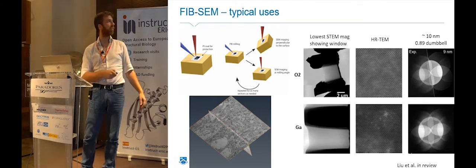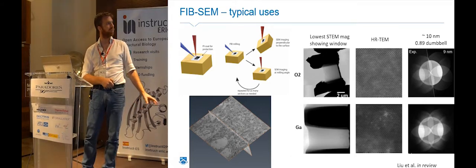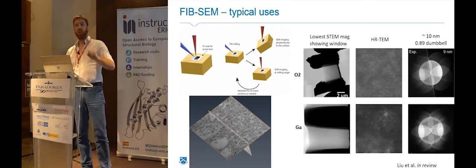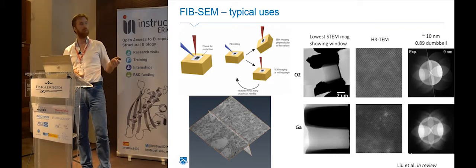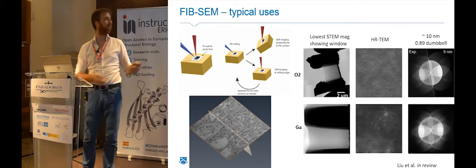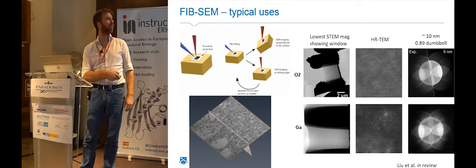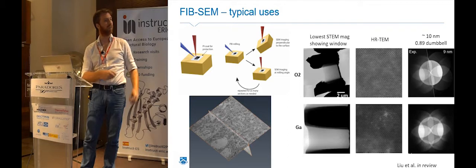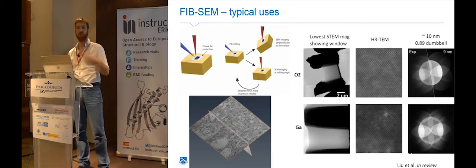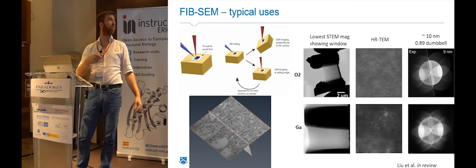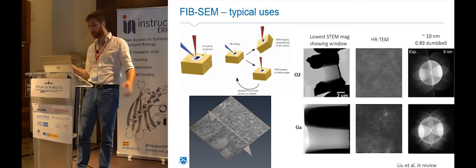In this case, just to highlight the implantation effect, this is diamond, and if you cut it with gallium, which is a metal, it will implant, and you will see this junk. You don't see a clean lattice, you see a lot of defects. That's due to implantation. If you use a different source, this doesn't happen.